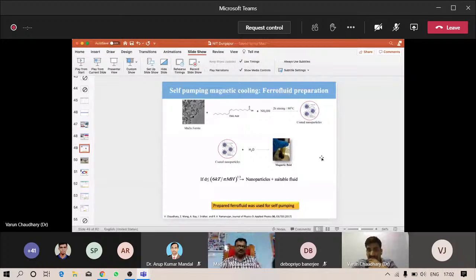Yes. Basically, if we just disperse the iron oxide in water, they will just sit down. You have done some vibration, magnetic stirring, and sonication. These things you have done mechanically. We did mechanical stirring here because magnetic stirring couldn't work because of the magnetic particles. So we did the mechanical stirring using a non-magnetic stick.